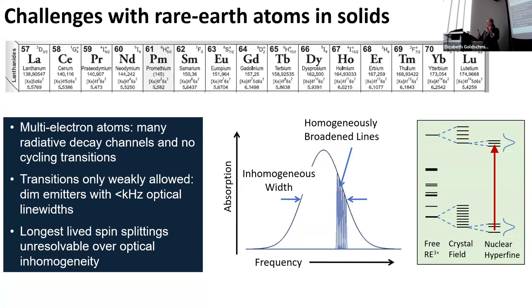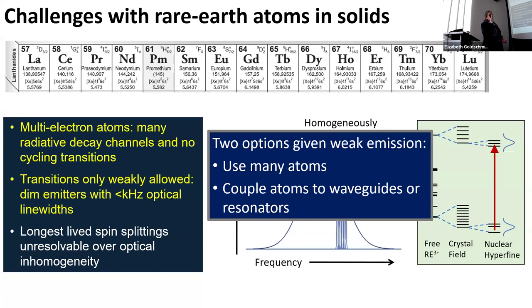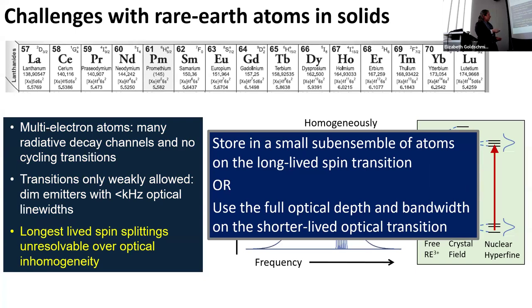So I have to do something to overcome these limitations. For the weak emission, I can use lots and lots of atoms, which is convenient because I can pack them in. Or I can couple to waveguides and resonators, which is natural because I'm living in the solid state. And then for the inability to resolve the really long-lived spin states over the inhomogeneity, I either have to use what's called spectral hole burning to select out just some very tiny sub-ensemble of atoms in some very narrow spectral region so that I can resolve the spin states. But that kills my optical depth. It kills the number of atoms in my ensemble.